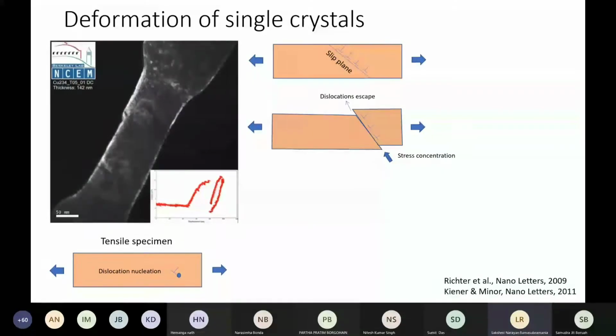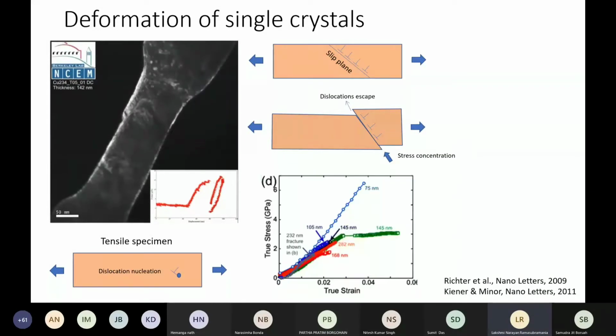And now what has happened is the cross-section area across this plane has reduced compared to that of the specimen, which means that this is going to experience higher stress because stress is nothing but force divided by cross-section area. And hence, this will lead to a further stress concentration in the sample and something called localization occurs.